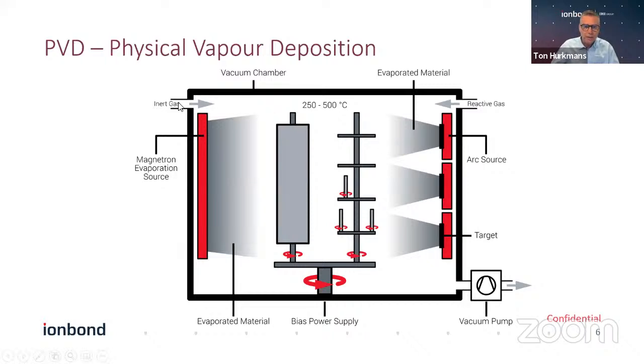Depending on whether we use just an inert gas, it will remain a metal as is, but we can also react it to a so-called ceramic material, a nitride, a carbide, a carbonitride, or an oxide, and form different materials on the surface of these parts. There are different ways to get a metal into a metal vapor flux. That can be either so-called cathodic arc evaporation, arc sources in short, or magnetron sputtering. For today's discussion, the exact difference is not so important, but it's important to remember that this runs under vacuum, with no nasty chemicals used in making these coatings.